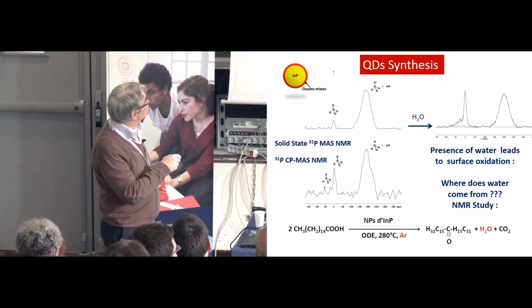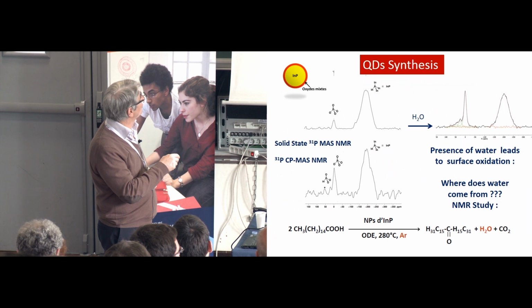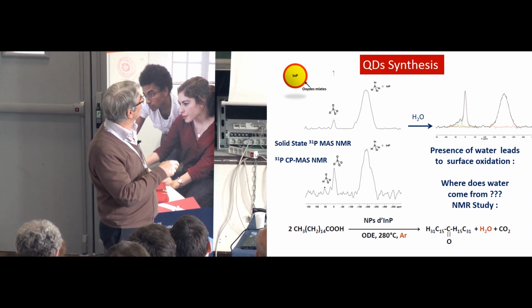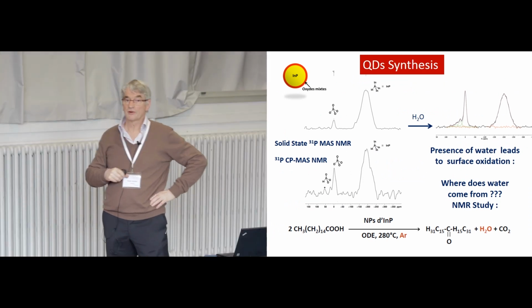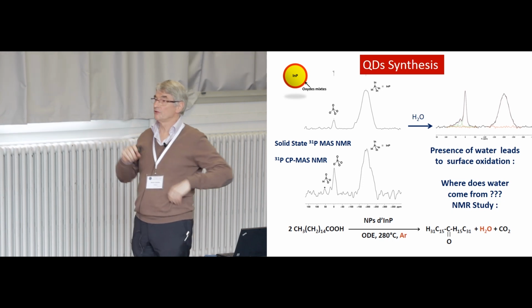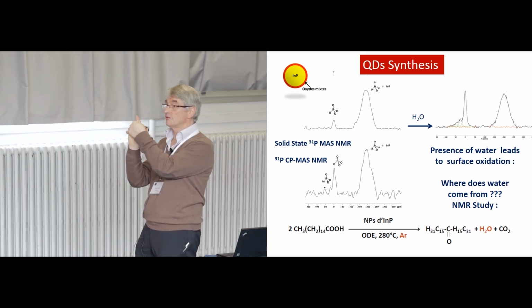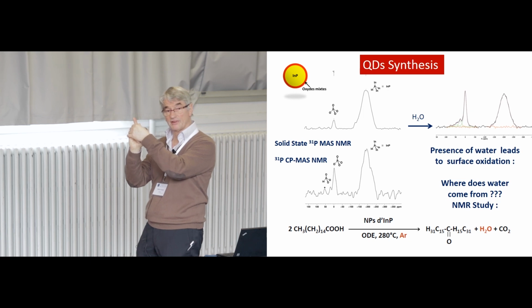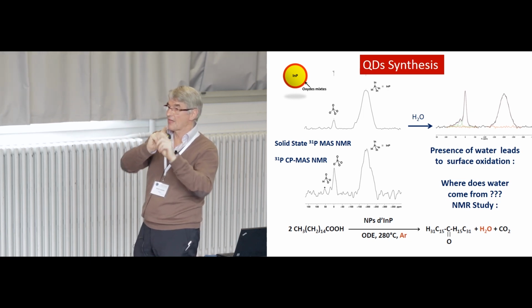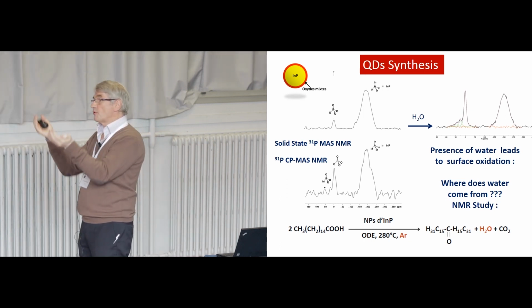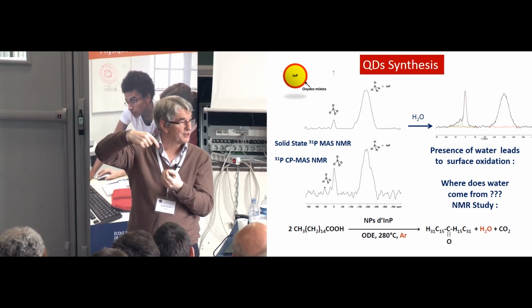To be sure that the phosphate is at the surface of the particle, what you can do is a cross-polarization experiment. You transfer the polarization of a proton, which has a high polarization, to the phosphorus. The protons are at the surface of the particle.